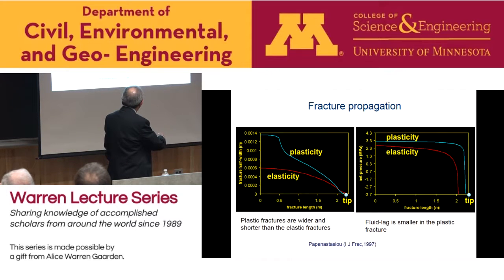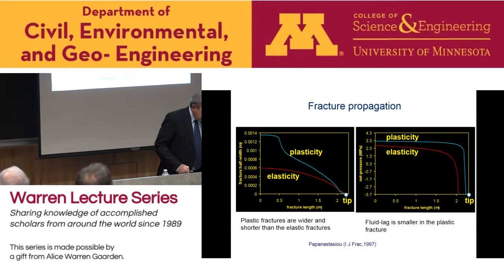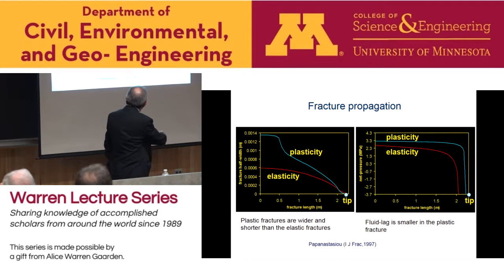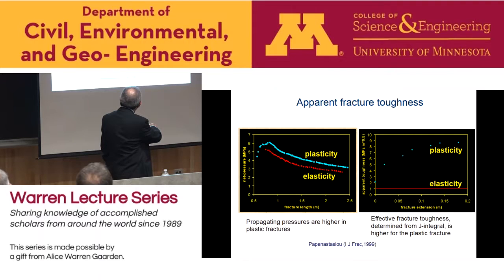If we look at the pressure profile in the fracture, here we have a fracture of 2.5 meters long, and this is the pressure profile as the fracture propagates. The red is the solution of elasticity, the blue is with plasticity. You can see the fluid lag with plasticity is much smaller than with elasticity. We have a larger fluid lag with elasticity. As a result, back at the wellbore there is not a big difference between plasticity and elasticity for the same fracture length. Of course, as the fracture propagates, the pressure predicted by elasticity is the red one, and with plasticity it's higher.